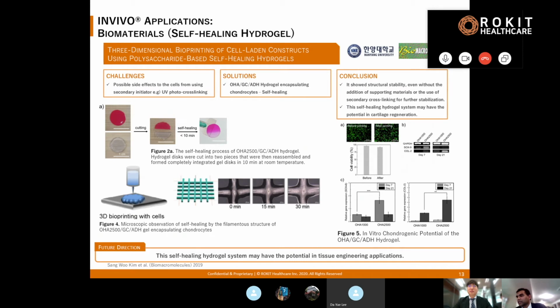because these are somewhat undesirable because they can damage the cells. So the ideal method would be something where the biomaterial can cross-link without the use of any of these agents. So with that in mind, the group at Hanyang University in Korea developed a self-healing hydrogel called the OHA, and the OHA stands for the oxidized hyaluronate and glycol chitosan, in the presence of adipic acid dihydrazide.